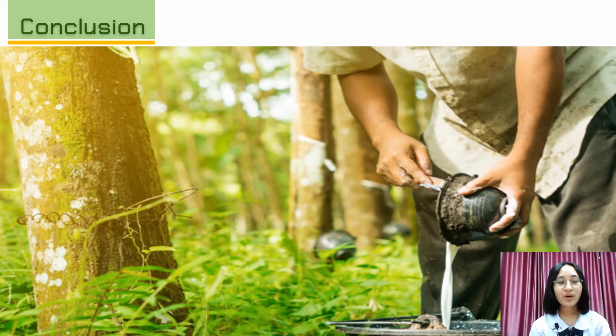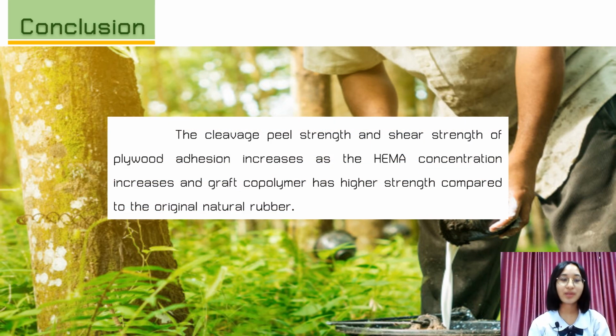We therefore conclude that the cleavage, peel strength and shear strength of plywood adhesion increase as the HEMA concentration increases, and the graft copolymer has higher strength compared to the original natural rubber.